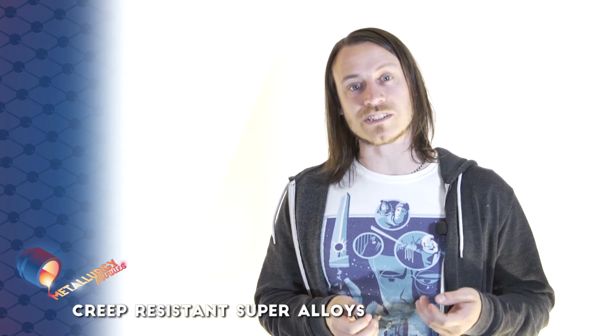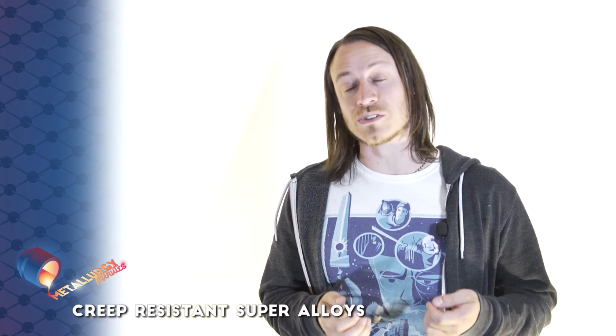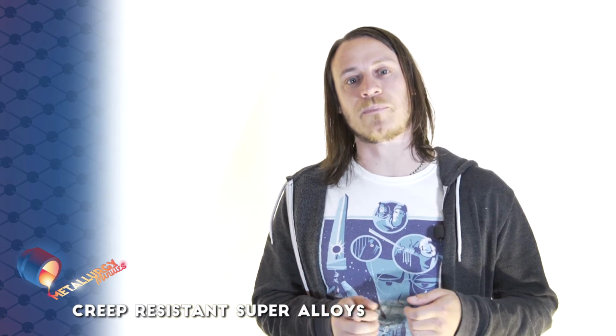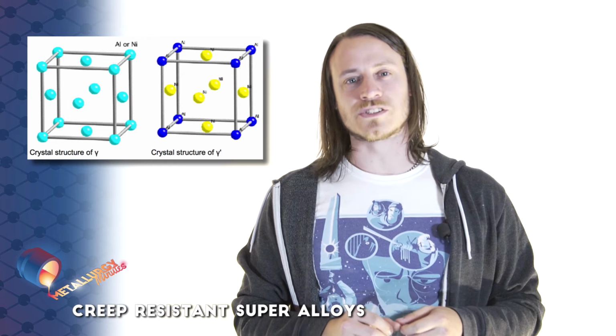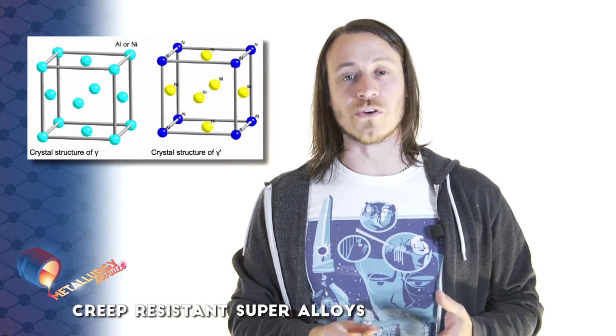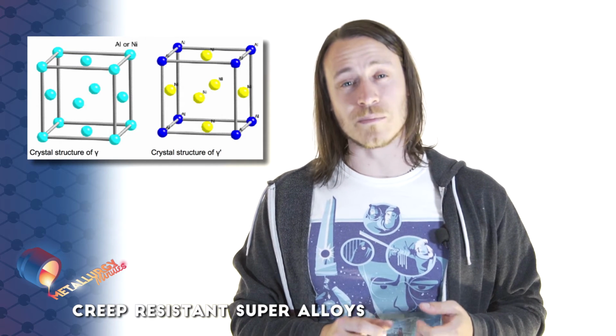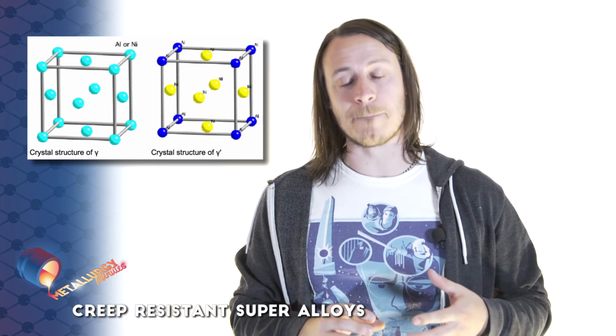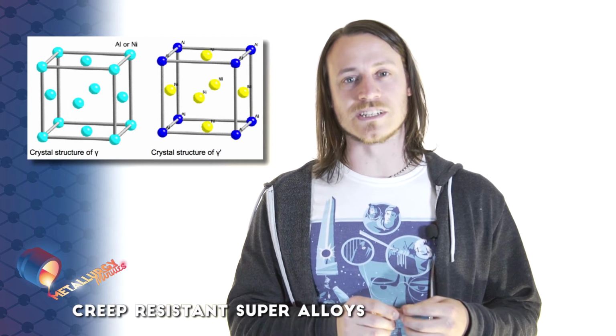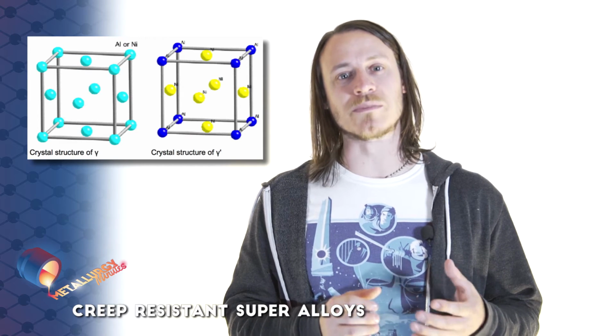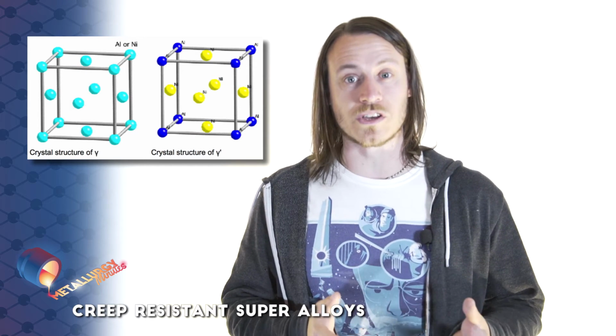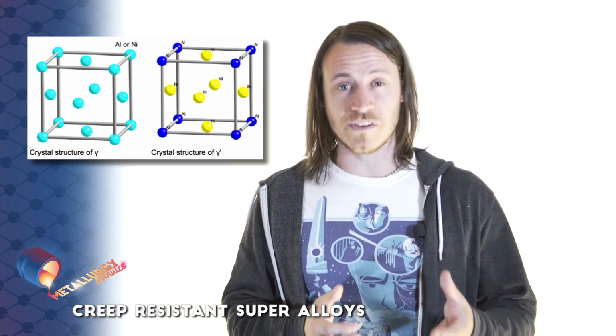Nickel-based superalloys are based on nickel with additions of aluminium and/or titanium up to 10 atomic percent. The gamma phase has a face-centered cubic structure where the nickel atoms are positioned at the corners and the faces of a cube, and the aluminium and titanium atoms are spaced within them. In contrast, the gamma prime phase is an intermetallic compound where the aluminium and titanium atoms are positioned at the corner of the cube and the nickel atoms are positioned at the face centres.